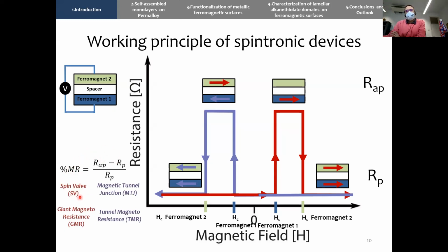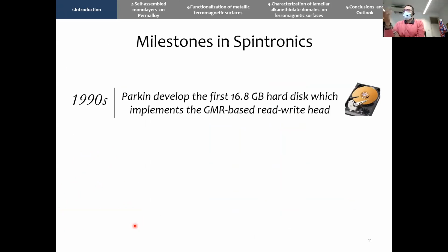Depending on the device we use, this effect will be called giant magnetoresistance or tunnel magnetoresistance. I comment this because in the 90s, giant magnetoresistance was used for the first time to achieve a high density hard disk, in this case 16 gigabyte, that until the moment was a breakthrough in the field, because thanks to this head, they could observe a difference of at least 3 orders of magnitude between the low resistance and the high resistance states.